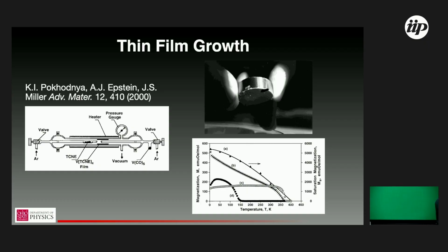About a decade later, in continuing to work with the material, they made, I think, one of the critical advances for the utility of this system, which is moving from solution synthesis to CVD, chemical vapor deposition growth. So this is a pretty simple setup because the deposition conditions here are quite mild. The pressure is a couple of torr of argon or nitrogen. The temperature is about 60 C, so that means this can all be glass, and you flow two precursors in. The TCNE, as I mentioned before, maintains its molecular character, so it is its own precursor. The vanadium is a little more complicated. The precursor there is vanadium hexacarbonyl, V(CO)6, which decomposes when it reacts with the TCNE to form your solid.